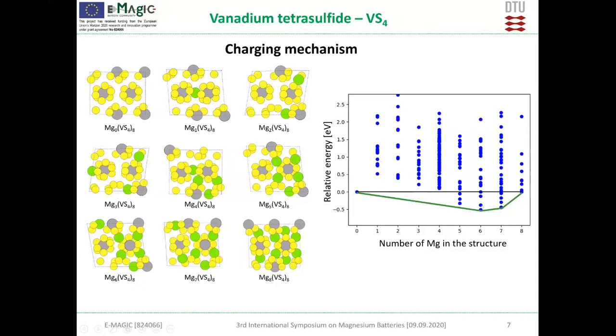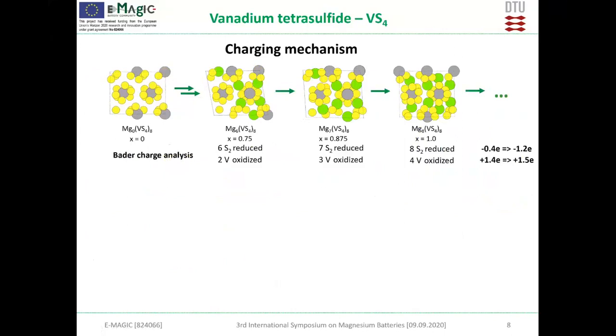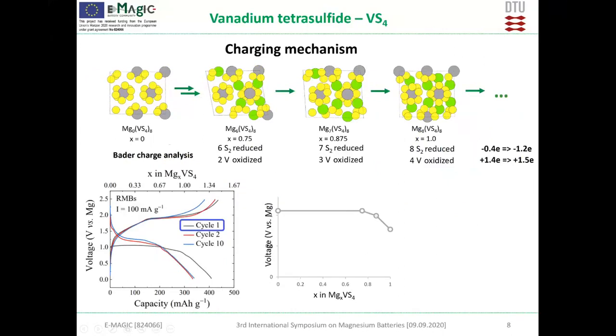That means this material has a very specific charging mechanism that at the beginning is heterogeneous, and then when we reach the phase that is stable, we are able to charge it homogeneously, so charging 1 magnesium by 1. Because of that, when we look at simulated OCV, we should have a plateau and then potential that is slowly dropping. And indeed, if you compare that with the experimental results from KIT for the first cycle, we can see that at the beginning we are seeing a plateau and then it's decreasing. We did calculation up to concentration equal 1. So we have quite good agreement for the potential that is close to 1, and here is 1. But what is interesting is what is happening here.